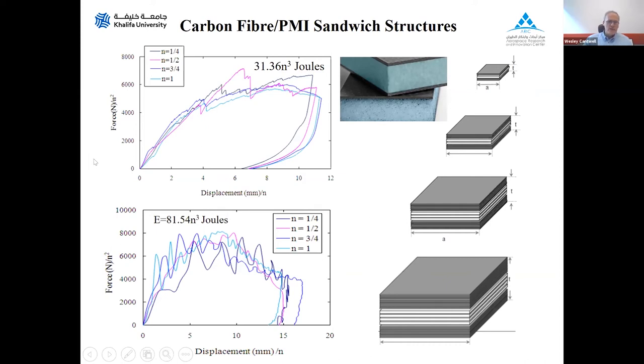We did impact tests on them just as we did before, measuring force against displacement. These are the normalized force, normalized displacement plots for the four scale sizes. And again, there's really quite a high degree of similarity, of overlap of our four traces going from the quarter up to the full scale, in spite of the fact that the N equals one, as I said, is 64 times larger in terms of mass and volume. If we increase the energy to almost 82 N cubed joules, we see again reasonably good similarity. You have problems really when you test the very small samples, but you can see some of these effects here. But nevertheless, it looks pretty similar.